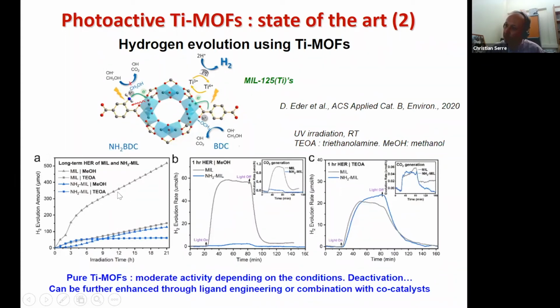But what you can see also is that this is not a linear production of hydrogen. There is a kind of deactivation or change in slope that is questionable here. What they showed is that there is little CO2 generation compared to hydrogen, so this is quite selective. But still, when people discovered the first titanium porous MOF at the end of the 2000s, there was a great hope that this MOF could be very interesting for photocatalysis and especially hydrogen production. And now this is a bit disappointing. There are some limited performances and there is some deactivation. And people try different strategies to improve that, such as ligand engineering or combination with co-catalyst. But still, this is not yet meeting the expectations that were raised before.